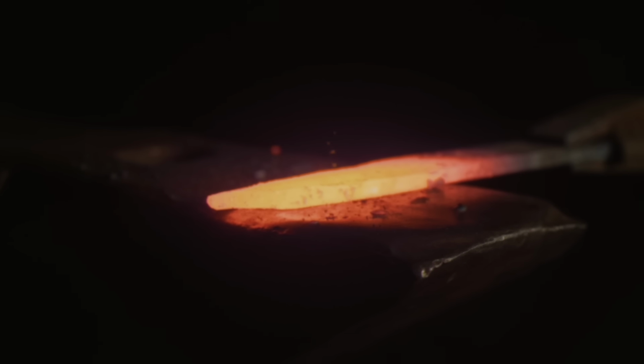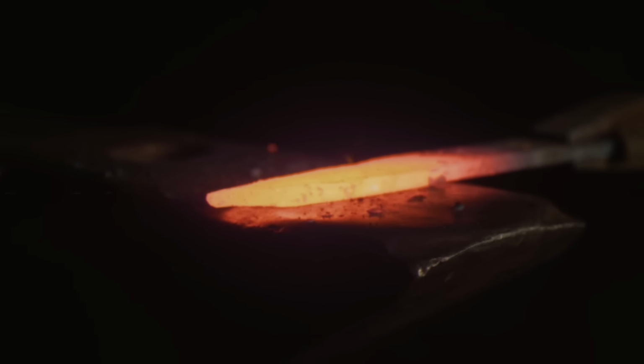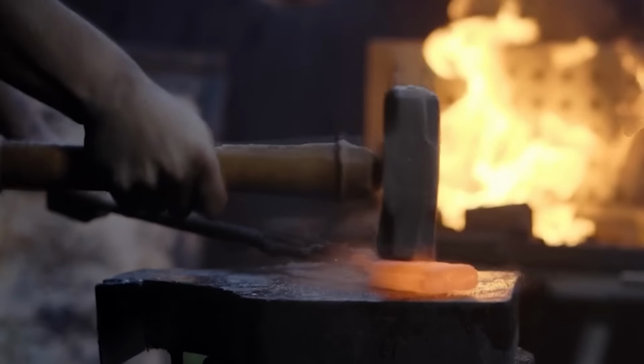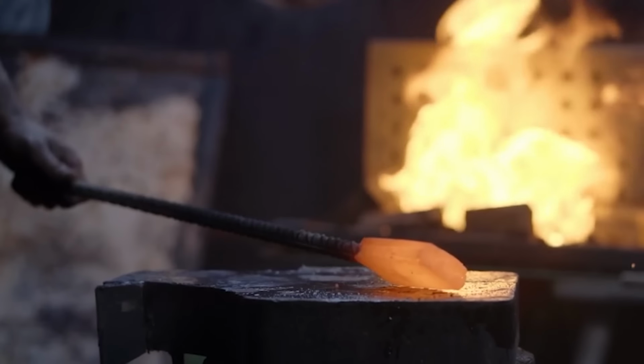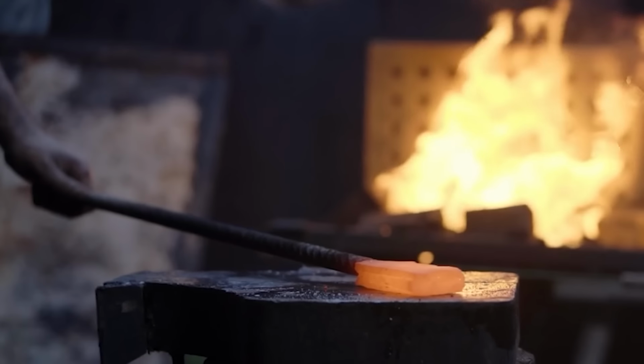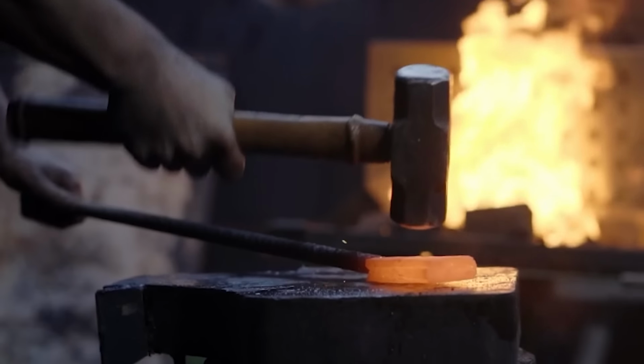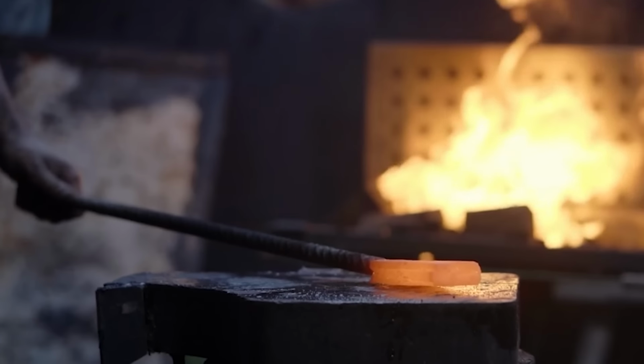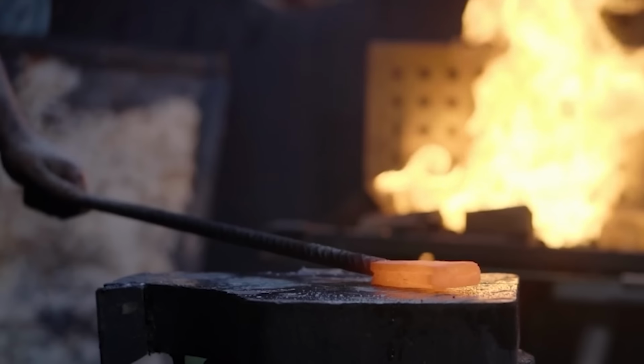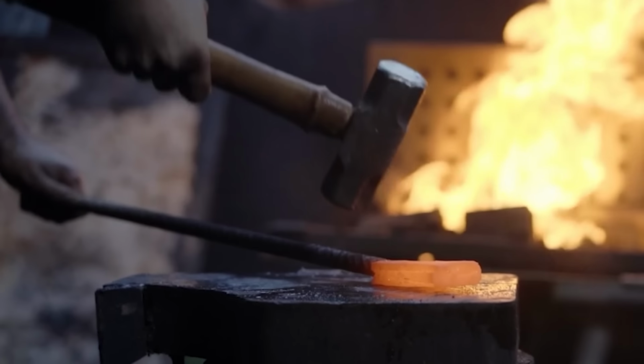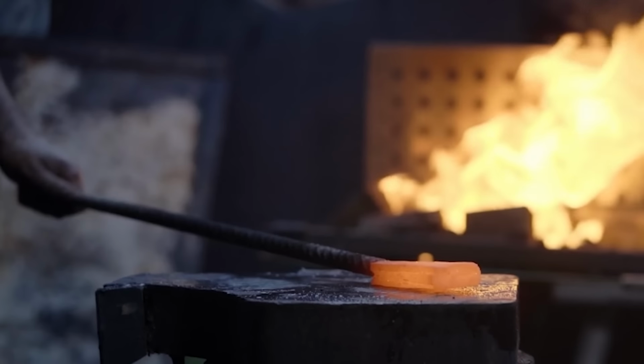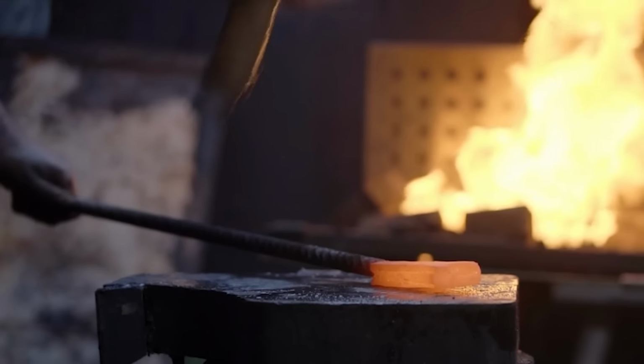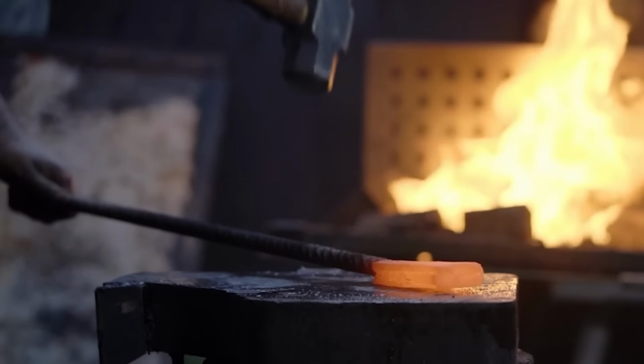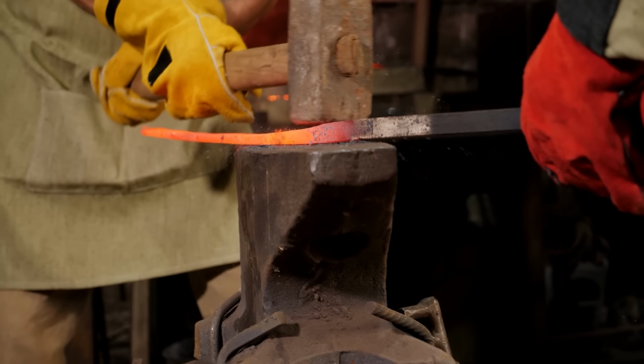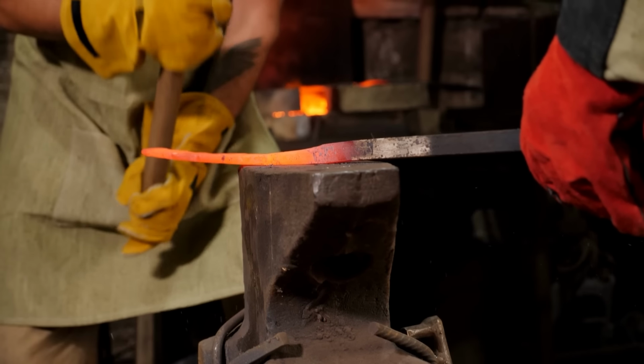The destruction tests measured 3 critical properties: flexural fatigue resistance, impact resistance, and edge retention. The first test measured flexion to failure. Each sample was flexed to 90 degrees, held for 10 seconds, released. The cycle repeated until fracture occurred. Sample B, the pressed piece, showed first visible crack after 12 flexion cycles. Complete structural failure occurred at 27 cycles. Sample A, the hammered piece, showed first micro crack at 43 cycles. Complete failure occurred at 89 cycles. The hammered piece demonstrated 3.3 times greater resistance to flexural fatigue.